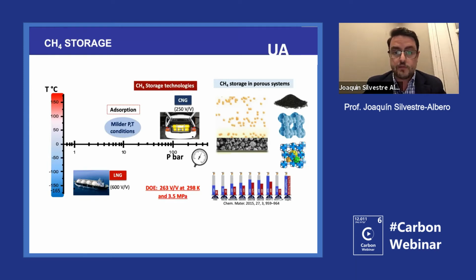No? And the main goal was to reach, as I say, a significant amount of methane per volume unit at atmospheric temperature and 3.5 megapascals. This is what the Department of Energy is defining. But there is also the possibility to shift to 6.5. So let's say that the main target is to design materials where we can play with these confinement effects. And the goal is to reach 263 volumes per volume, which is rather similar to the compressed natural gas. But as I say, instead of working at 20 or 25 megapascals, to do the same at 3.5 megapascals or maximum 6.5. No? So this is our main objective in the preparation of carbons.